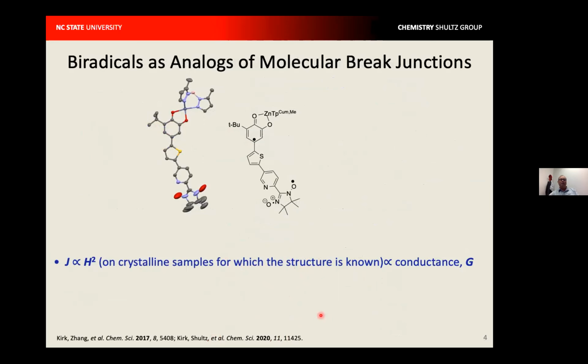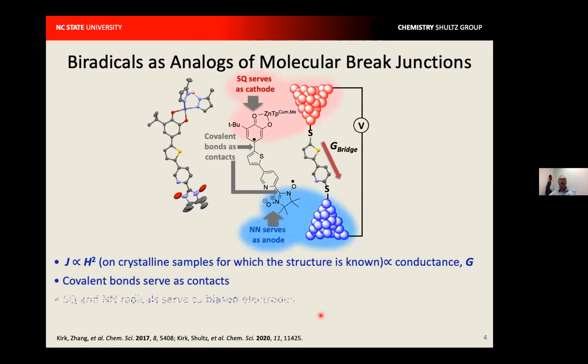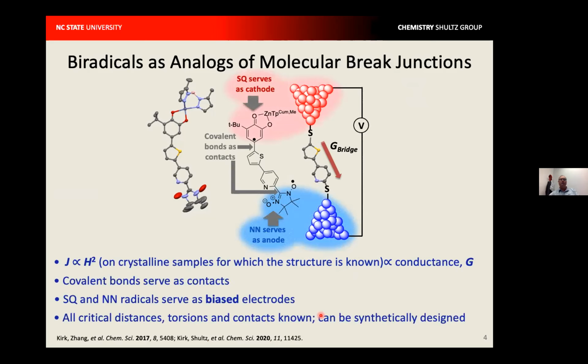So just to show you very briefly what we're doing with the donor acceptor biradicals, we've counted these molecules as analogs of molecular break junction devices, where the radicals behave as the electrodes and the molecular bridge fragment mediates the magnetic exchange coupling between the donor acceptor biradicals. And because that exchange coupling is proportional to the square of the electronic coupling, and because the conductance, the electron flow through the bridge, is proportional to the electronic coupling,